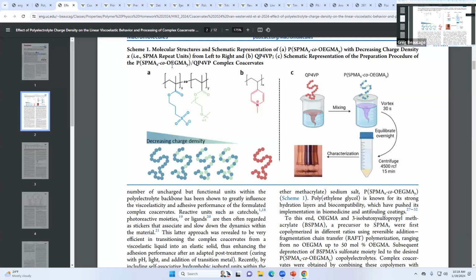So to do that, they take the same reaction, this wolves feeding, but they take the wolves and put them in cages that open periodically so that the wolf can go eat and then close up again. So it's got a protective thiol group that protects the free radicals as they float around. RAFT polymerization is really popular because these are the workhorse polymers, like acrylic. And you can do it with ethylene, styrene. So you make monodispersed polystyrene, whatever, one molecular weight. The only other way to make monodispersed polymers is by ionic polymerization, anionic or cationic.